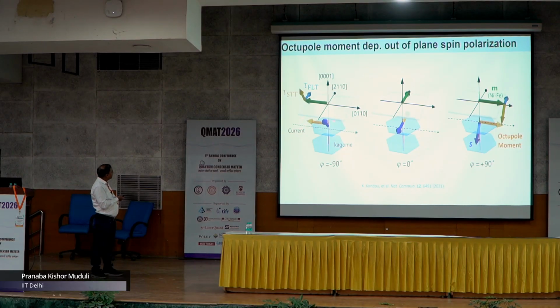This is the current direction shown by this dotted line, the octopole moment is this yellow one here, and the blue one is the spin current that is generated. When current and octopole moment are parallel or anti-parallel, you generate a spin current which is out of plane. But when they are perpendicular, like in this case, you generate a spin current which is in the plane. So you generate out of plane spin current when the current and the octopole moment are collinear. This is the observation they had made.